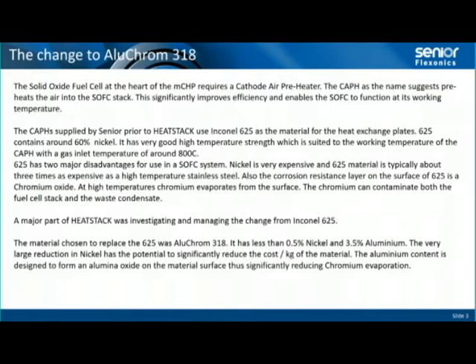Okay. So as I was saying, before HEATSTACK started, we were supplying Vaillant with heat exchange plates made from Inconel 625. 625 contains around 60% nickel, so it has very good high temperature strength, which is suited to the working conditions of the cathode air preheater. Gas inlet temperature is typically around 800 degrees C, but it has two major disadvantages. The nickel, of course, is very expensive, and so it makes 625 expensive. And the corrosion resistance layer on 625 is a chromium oxide, and at high temperatures the chromium oxide can evaporate, and the chromium then contaminates both the fuel cell and the waste condensate.